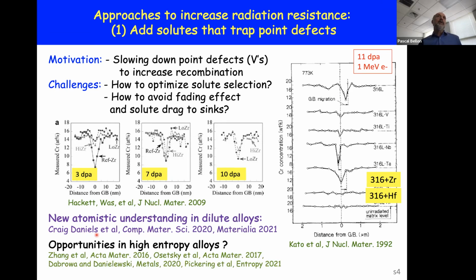This approach has also recently been considered as a potential strategy for high entropy alloys, where there have been some reports that the high entropy, or the disorder that exists in a high entropy alloy, can slow down point defects and promote recombination and thus radiation resistance. There is still an active ongoing discussion as to whether this is really the reason why high entropy alloys may have good radiation resistance, and I'll simply point you to the references listed at the bottom of the page here.